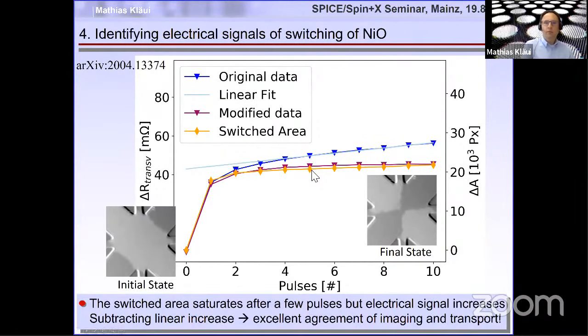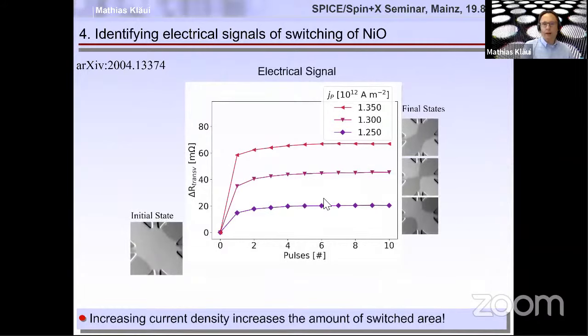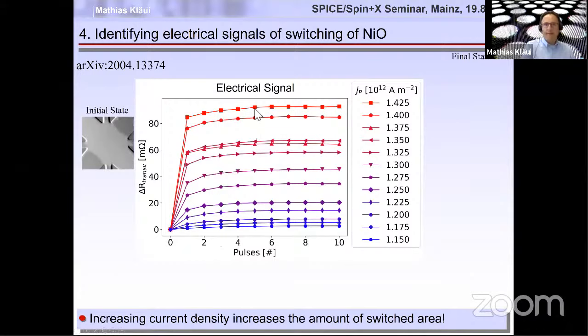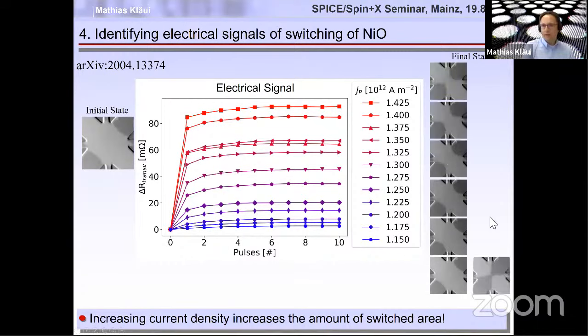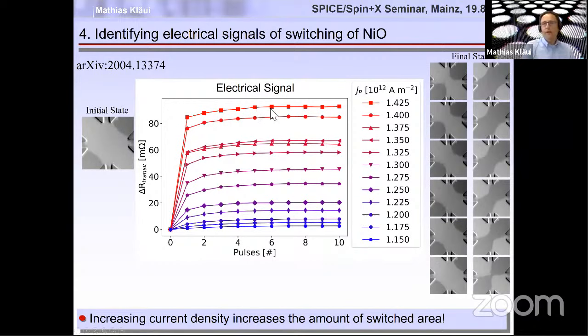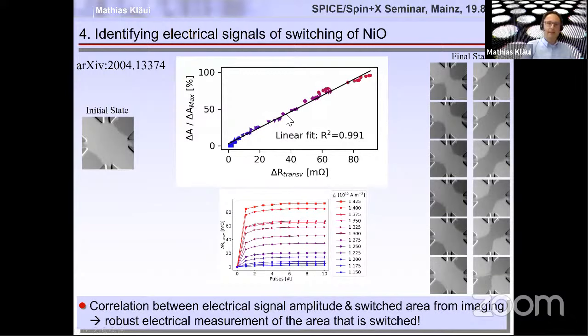To show that this really works, we did this for a lot of different current densities. If we start with low current densities, we see only a tiny bit of switching. At intermediate current densities, the center has already switched. And at high current density, virtually the whole area inside the cross has switched. We did this for many, many current densities, and we see that we get more switching for higher current densities. Initially, there is little switching, and as we increase the current density, the amount that is switched continues to increase until the central area is fully black. Now we compare how much of this corrected electrical signal corresponds to how much of the imaging-detected magnetic switching. We get a perfect linear fit, with a high correlation between the electrical signal and the magnetic signal. So this means there's a robust electrical measurement of the area that is switched.